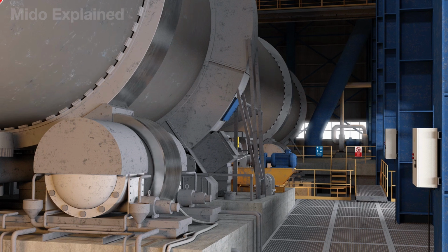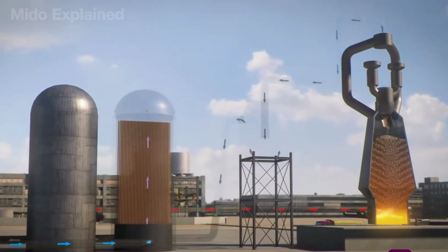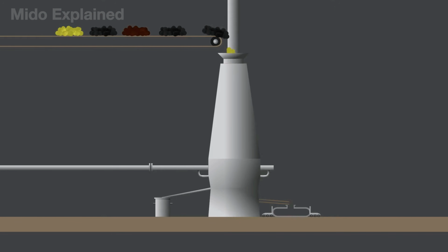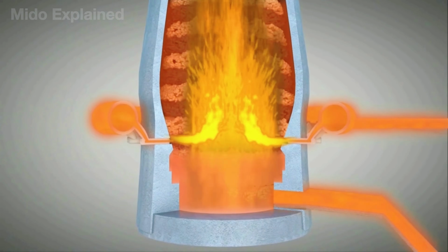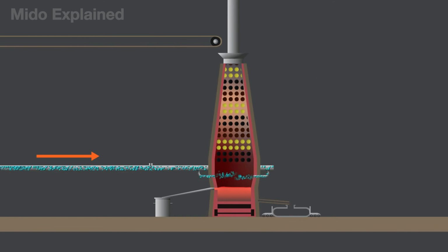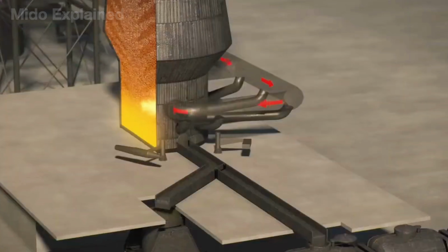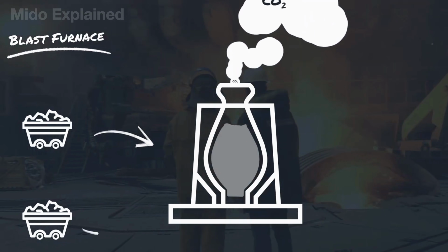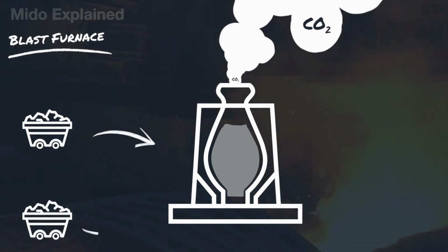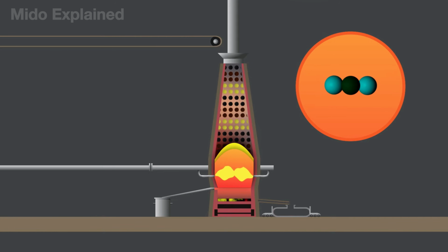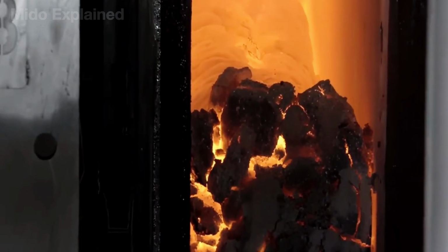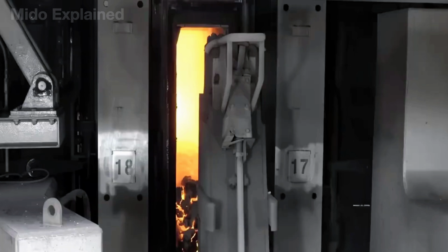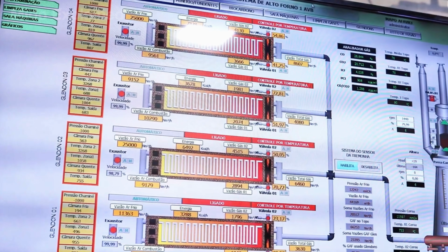Once hard enough to withstand extreme heat and pressure, these ores are finally ready to enter the blast furnace. From the top of the furnace, iron ore is fed in layers along with coke and limestone. Meanwhile, air heated to about 2,000 degrees Fahrenheit is continuously blown in from the bottom of the furnace to burn coke. When moving to the bottom of the furnace, the temperature increases to nearly 2,800 degrees Fahrenheit, enough for iron to melt and accumulate into liquid iron, while limestone combines with impurities to form slag that floats to the surface. The interesting thing is that a modern blast furnace can operate continuously for more than 15 years without being turned off.